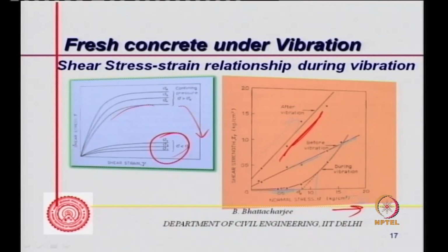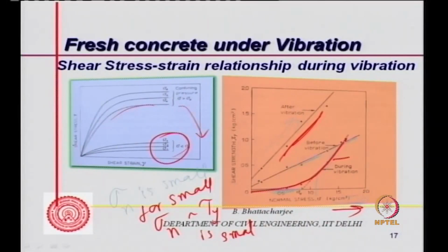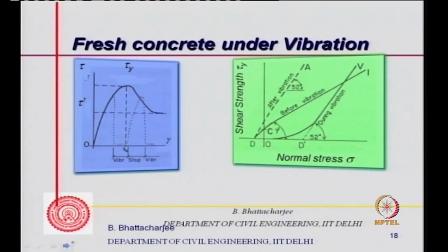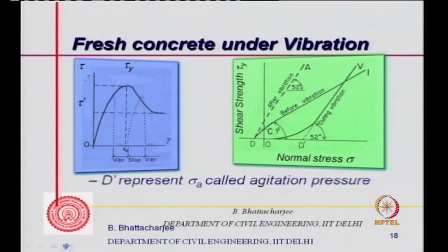So this is my sigma. After an increase in the sigma value, you find that it behaves almost, not exactly parallel to this, but in some way like this. So when the normal sigma applied is small, for small sigma n, tau y is small during vibration. It behaves like this. And up to a certain normal sigma value, practically there will be no yield shear stress. Now this sigma value corresponds to the equivalent force of vibration. We define this as agitation pressure.